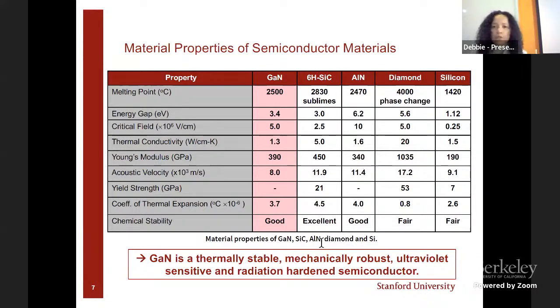How does gallium nitride measure up in terms of our modern day semiconductor materials? So this is our silicon here, our band gap of 1.12 eV. Again, that translates to around 200 degrees C thermal limit, whereas gallium nitride has a wider band gap of 3.4 eV. Also the very high melting point. It takes a lot of energy to break apart the gallium and nitrogen atoms. And also this also enables its radiation tolerance, which is nice. The 3.4 eV also translates to the ultraviolet spectrum. So the ability to make UV photodetectors that function at elevated temperatures. This was really attractive to me.